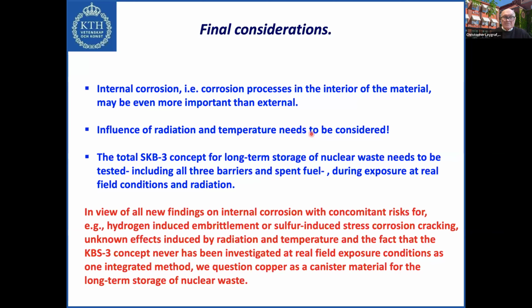And our conclusion from this is that, in view of all new findings on internal corrosion with concomitant risks for hydrogen-induced embrittlement or sulfur-induced stress corrosion cracking, or unknown effects by radiation and temperature, and the fact that the KBS3 concept never has been investigated at real field exposure conditions, we can question copper as a canister material for the long-term storage of nuclear waste until more evidence has been presented, much more evidence.